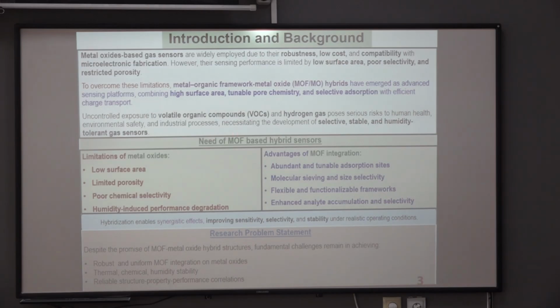To overcome these limitations, there are a variety of approaches we can employ, including heterostructure formation, noble metal doping, rare earth metal doping, and so on. One such way is metal organic framework metal oxide hybrid systems, in which metal organic framework integration provides abundant and tunable adsorption sites, a molecular sieving effect due to the high porosity of the metal organic framework, and hence analyte accumulation.